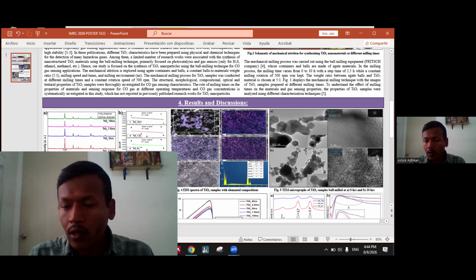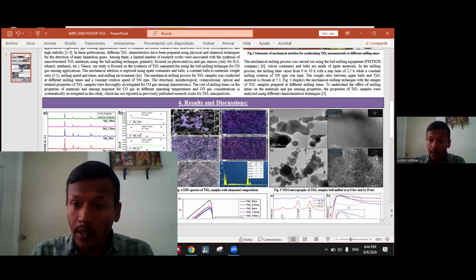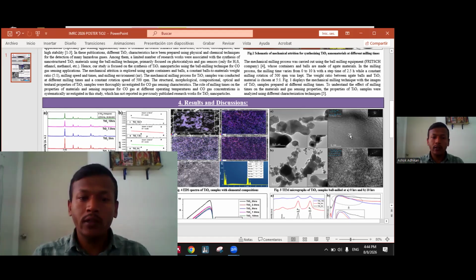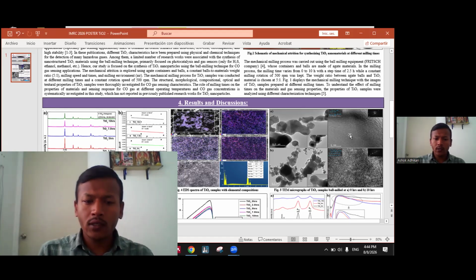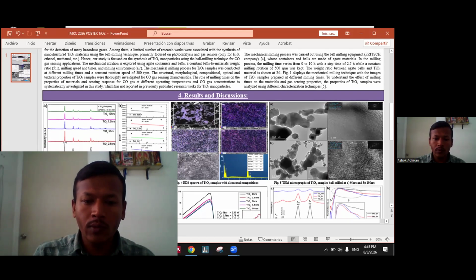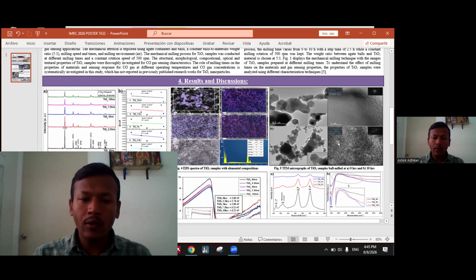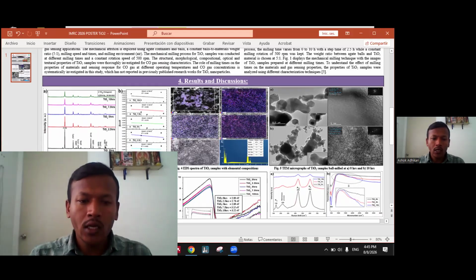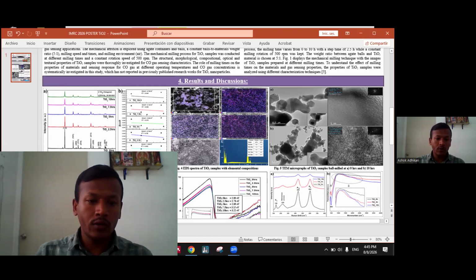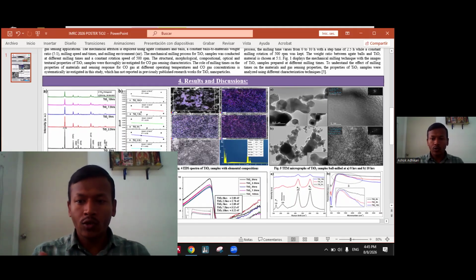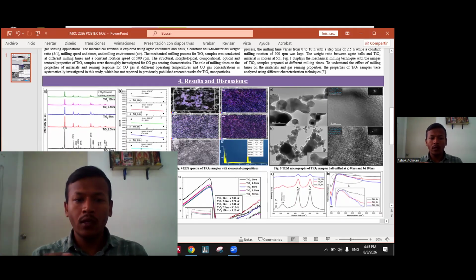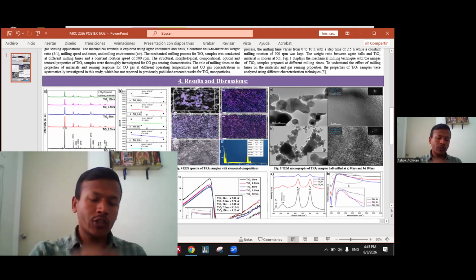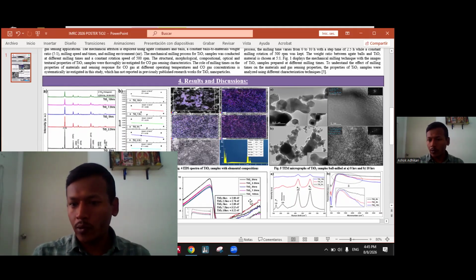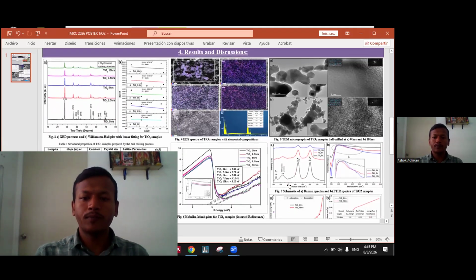And from the high resolution TEM image, we have also calculated the interplanar distances. The obtained values are similar to the interplanar distances obtained from the XRD results. So from these results, we can also confirm the XRD structural and morphological properties of the TiO2 samples.